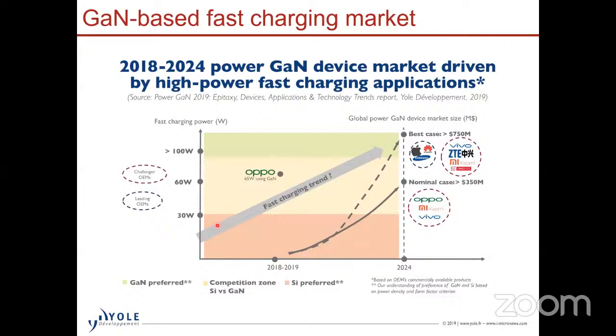So early on, we mostly had slow chargers that were based out of silicon, because silicon is cost effective and it works well in this wattage range. But as we move from 30 to 100 watt, there is a competition between silicon and gallium nitride, with gallium nitride being more efficient but silicon being more cost effective. There is a trade-off between the two. But the Chinese companies are favoring GaN, and they believe that when we go to more than 100 watt charging, it's going to be gallium nitride's market.